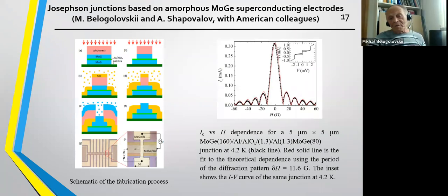We need more explanation. Maybe it is not a quantum situation, but something like a non-Hermitian system with edge currents. The last thing I wanted to tell is about Josephson junctions based on amorphous molybdenum germanium superconductors. It is the first Josephson junction based on amorphous superconducting films in the literature. And the results were excellent, very trivial and very excellent. So it can be that in future we can transfer from niobium layers to amorphous superconducting films. The Josephson junction should be based on them.